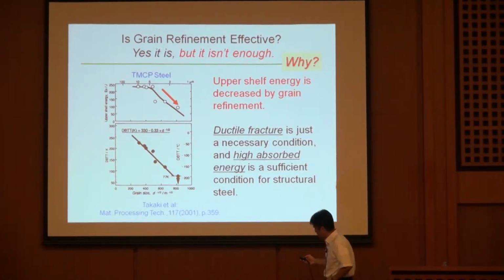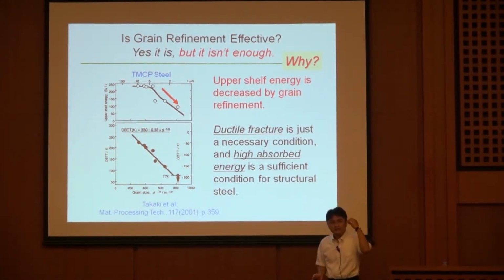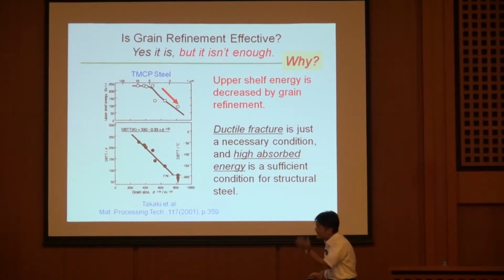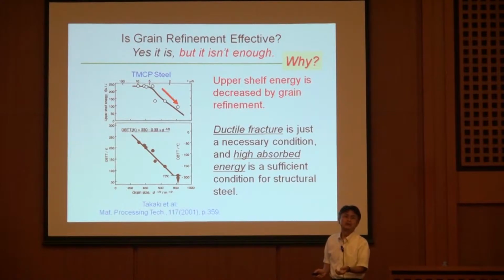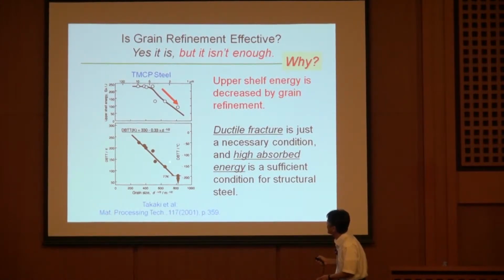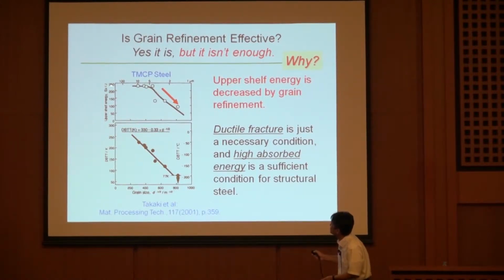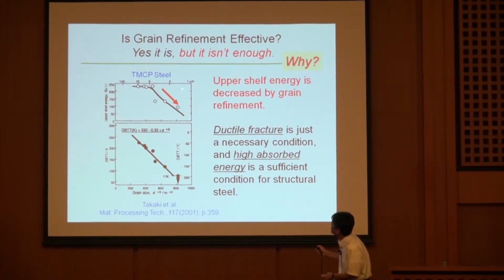But when you look at the absorbed energy, well, this is telling you a transition in the fracture mode. This doesn't say anything about the absorbed energy in the ductile mode. This is the energy. Energy is higher than 200 joule when the grain size is around 5 micrometer. But this value decreases like this with the grain refinement, and then goes lower than 100 joule.